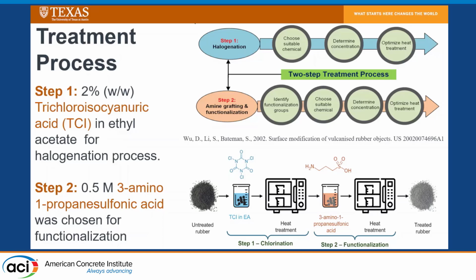We're doing the second step of the process, and at the end you have treated rubber. And after we identified the chemicals, the key thing was to try to figure out what was going to be the major parameters for this heat treatment process, and particularly the exposure time as well as the temperature.